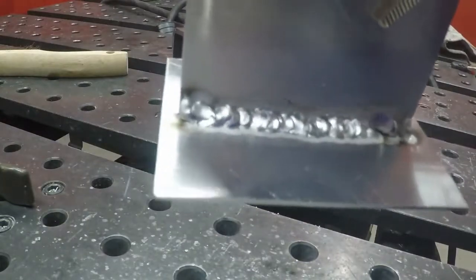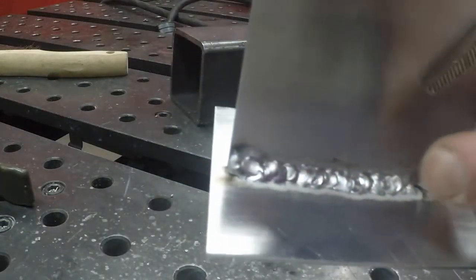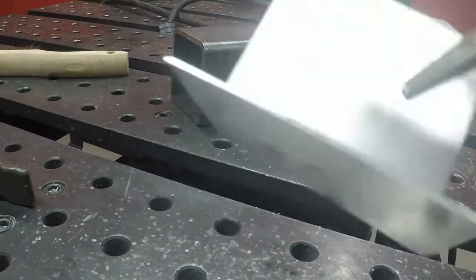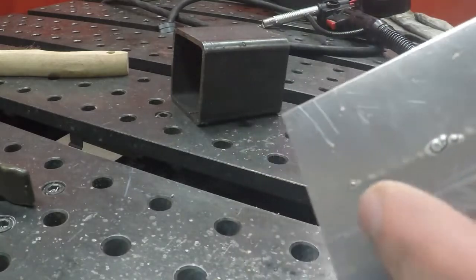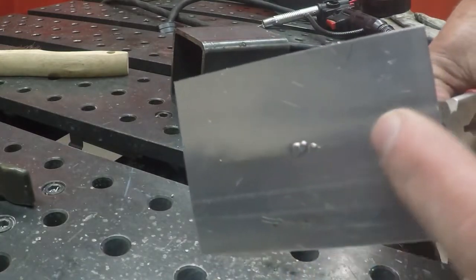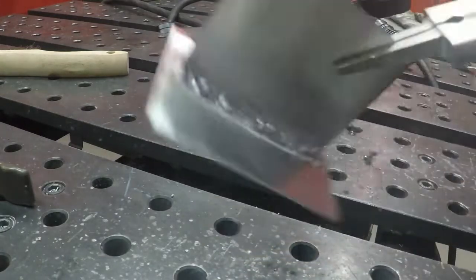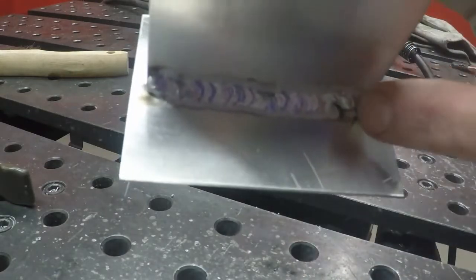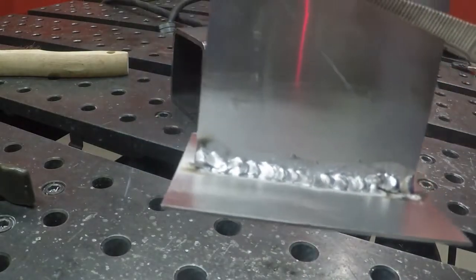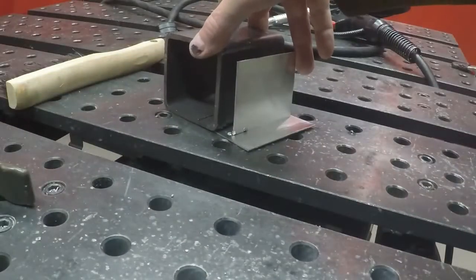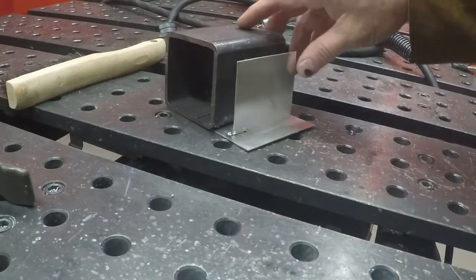So you can see that I've made a wider weld in through here in order to bring my heat up. Down on the bottom, you can see the line across the bottom where I'm starting to get penetration. And if you look really carefully, I'm not quite deep enough into the corner there, but all in all, that's not too bad. I don't have to tack weld again on this side because I've already tacked and welded it on the other side.